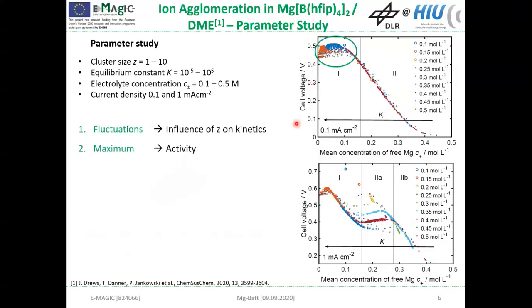So the first eye-catching feature is that there are some fluctuations here, and this is caused by the influence of the cluster size on the electron transfer kinetics. Moreover, we see that there's a maximum of the overpotential, and the reason for this is that we included the non-ideality into our model. An additional feature can be found at a high current density. So this pronounced slope can be assigned to transport limitations in the electrolyte.